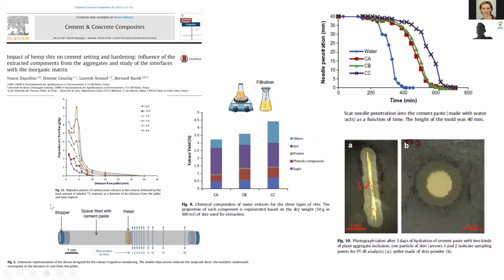What we have seen is that, according to the retting degree, the hardening of the concrete is retarded by the presence of extractives, and these extractives are coming from the rating of the material. If the plant is retted, then you extract more molecules, and all these molecules are retarding the hardening of the material. Here, as an illustration, you see sheaves that are put into a pastille and then included in Portland cement.